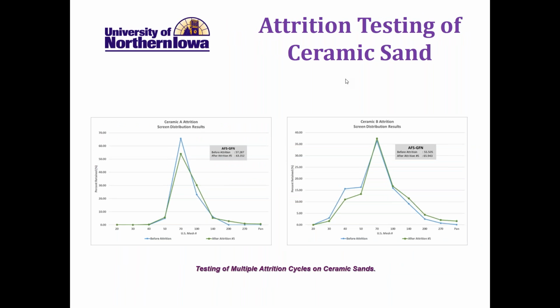We can compare the ceramic A attrition with the ceramic B, and you can see the changes. Ceramic A resulted in quite a bit less on the 270 and pan. The 270 and pan screens are representative of the silica dust that can be generated with that sand. It is not respirable at that sizing, but it is representative of the amount of dust. We can see on ceramic B, we had quite a bit more on that 200, 270 and pan. So that material was breaking down to a finer extent than the ceramic A.